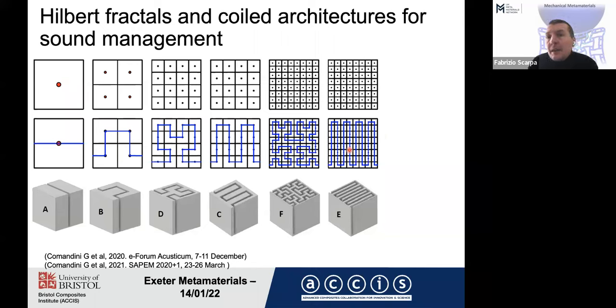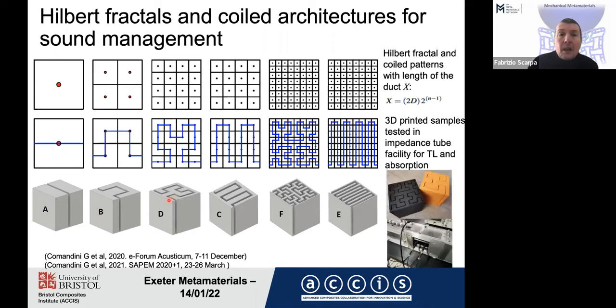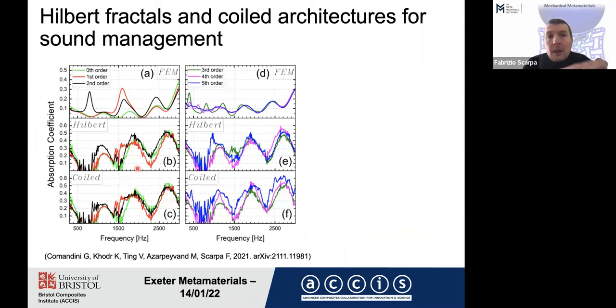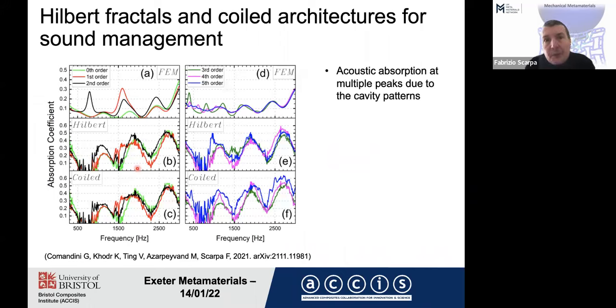And this one, they have the total length of the cavities equal. So we have considered these two configurations really as a benchmark to assess whether fractality plays a role in the acoustic absorption. So we have done tests in impedance tubes and developed also finite element models considering pure acoustics and also viscothermal acoustics with a sort of boundary layers, especially at the interface of the internal cavity.